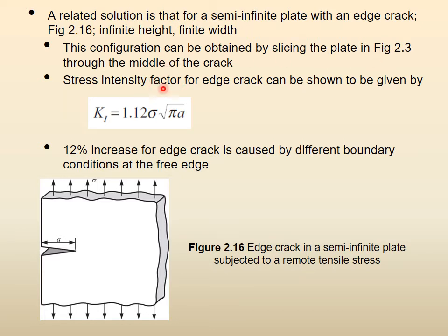A stress intensity factor for an edge crack can be shown, we are not deriving it, can be shown to be given by this, that now the factor is 1.12. If it is an edge crack, the factor is 1.12. The factor is 1.12 root pi a, right?